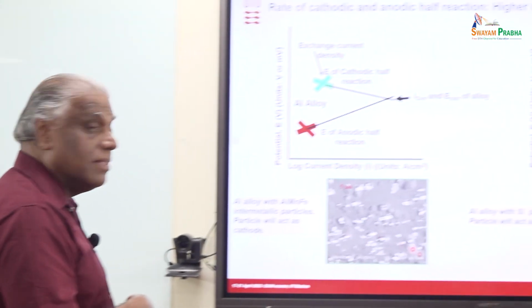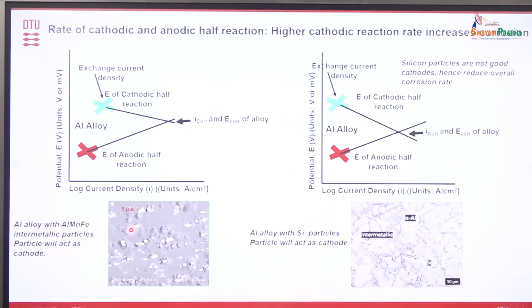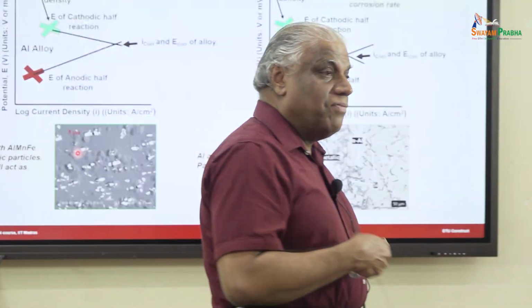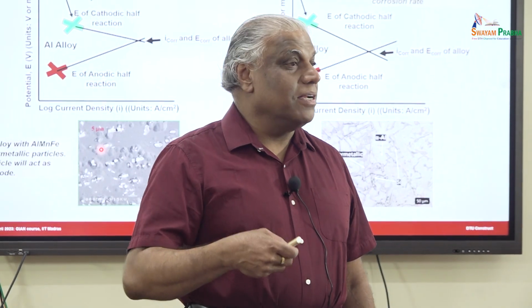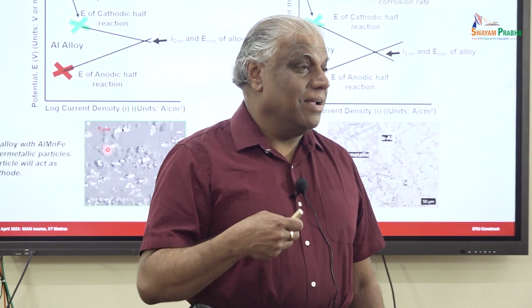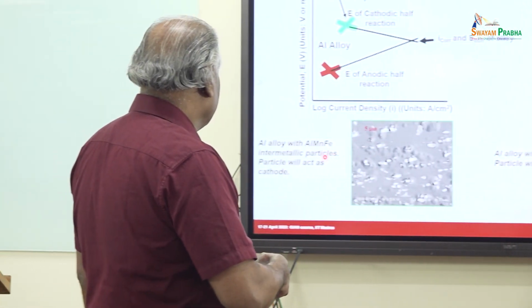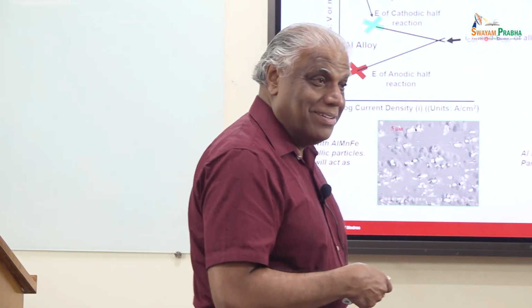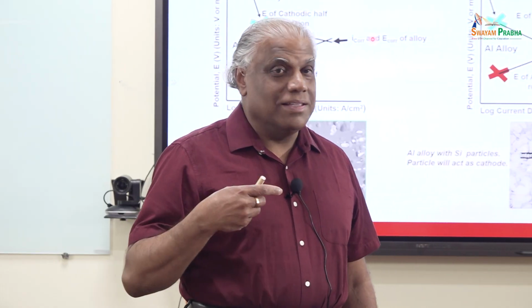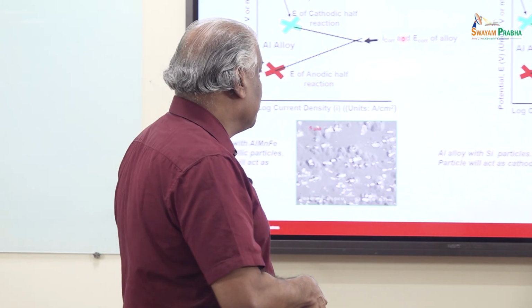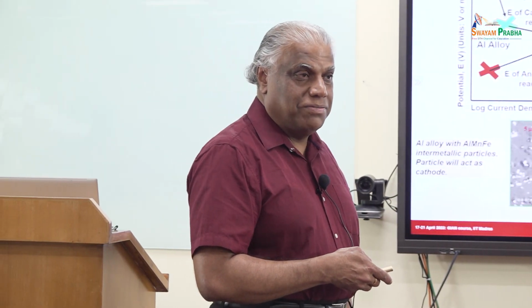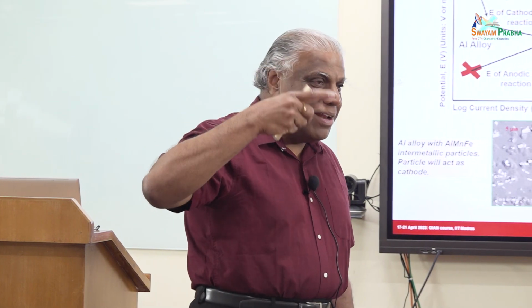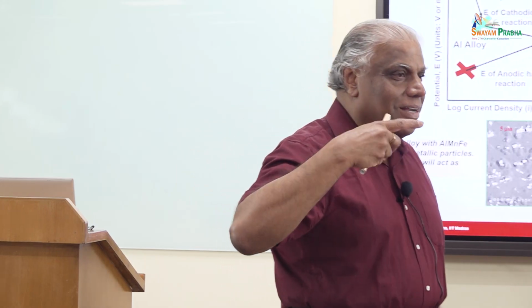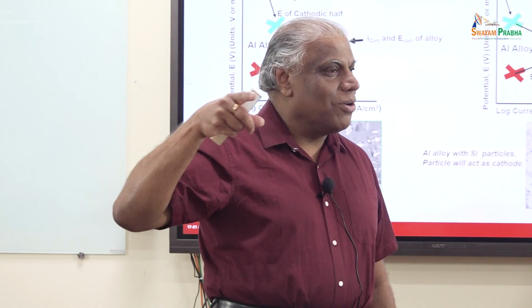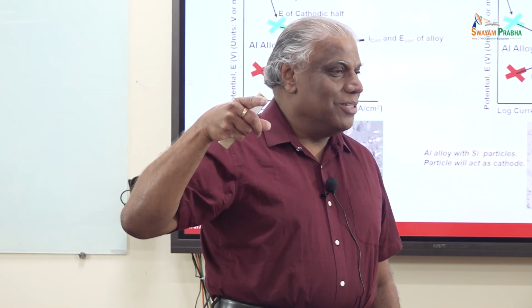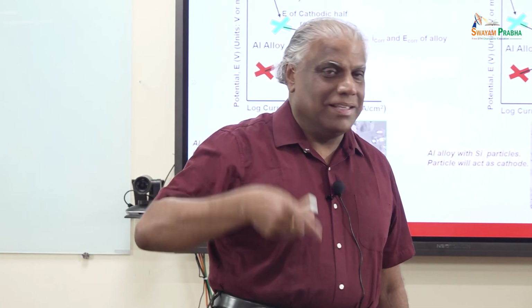And this is a typical issue in aluminum alloys, because aluminum alloy can have iron impurity as well as silicon impurity. Sometimes after recycling you get more iron impurity, and sometimes you get more silicon impurity with less iron. People see that whenever you have less iron, it still forms similar types of particles with silicon, but the corrosion rate is lower. Those alloys are better than the iron ones. So having more silicon impurity is okay compared to iron, exactly because of this problem: silicon is not a good cathode. You can see how important this is when companies are thinking about making a recycled alloy; they need to understand this. Okay, maybe I can have a little bit more silicon from the recycling process. That's okay to allow, it's not that sensitive to corrosion, but I need to control the iron.